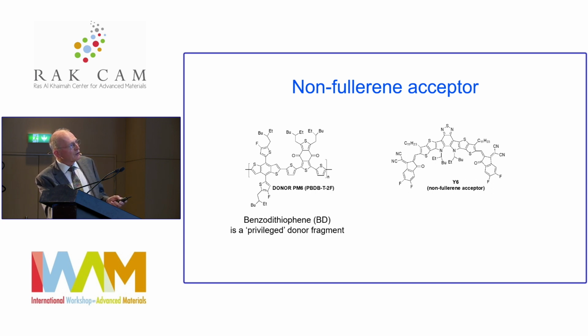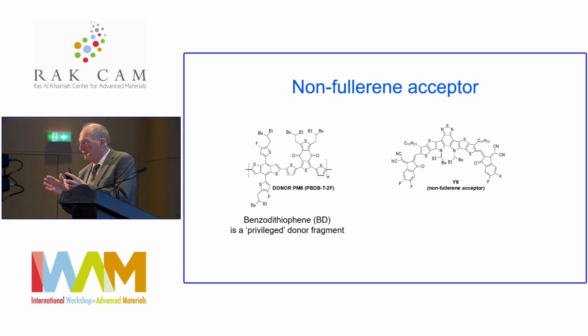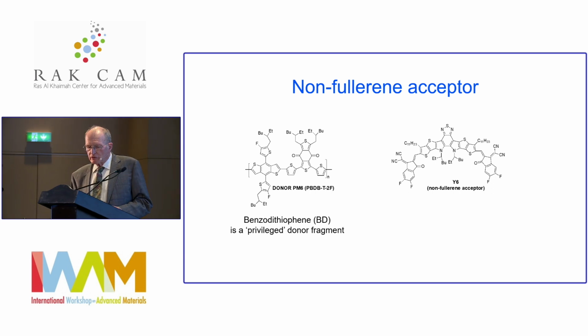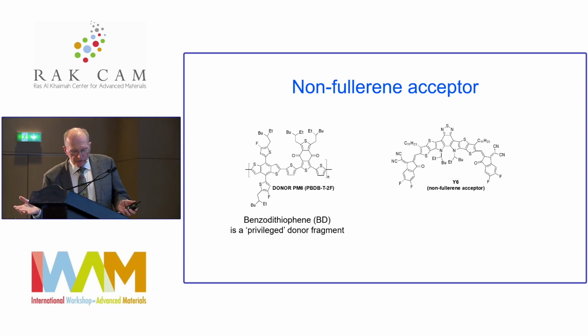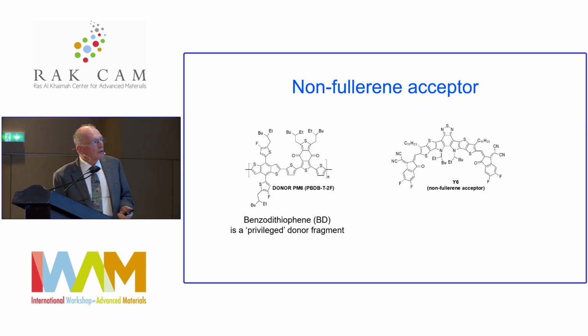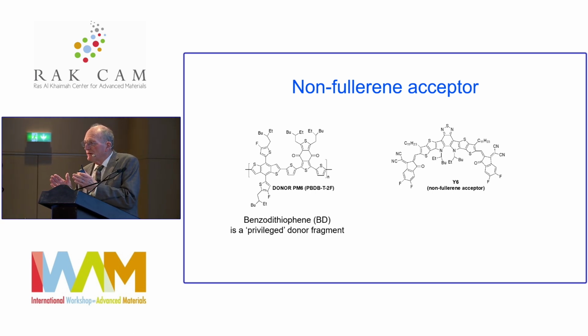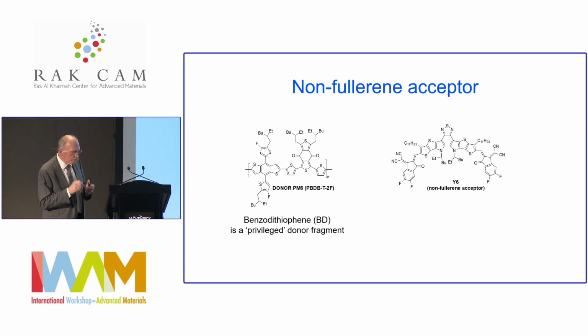And the other trick is to have attached to it something that's a little bit more electron withdrawing, and the combination of those two groups in the same polymer means that the gap for excitation is nearer the absorption maximum that's used in silicon, around about 700 nanometers or so. So having those in the same polymer means that the excitation energy is similar to that needed to excite silicon when it absorbs sunlight.